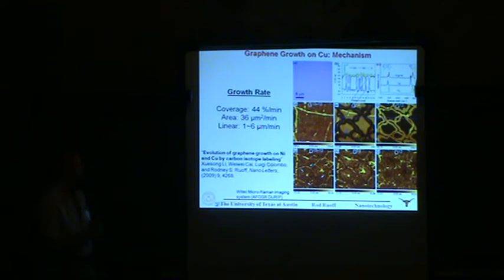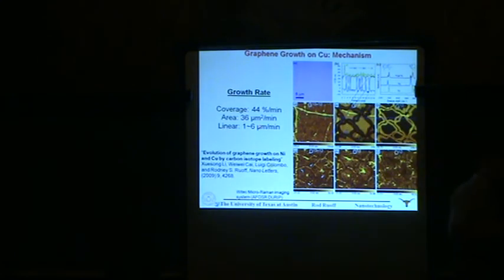What's kind of fascinating also is the presence of these wrinkles. Why do wrinkles show up? They show up because the coefficient of thermal expansion of copper is much, much larger than that of graphite. In fact, graphite is a very unusual material. Between about room temperature and 700 Kelvin, graphite has a negative coefficient of thermal expansion. So as you heat it up, it contracts laterally. And graphene actually does the same thing at room temperature. It's not yet mapped entirely in terms of the temperature dependence the way graphite has been. Right, or a tremendous stress.